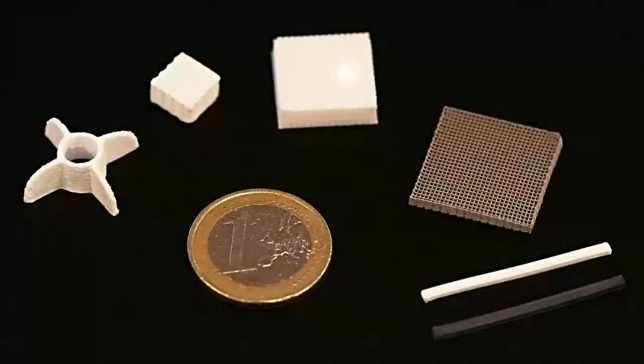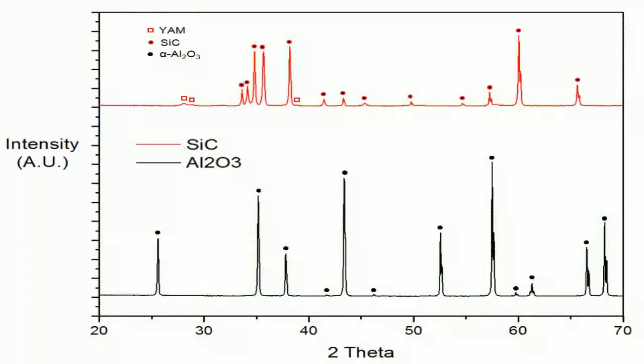And did they find anything interesting about the platelets themselves? Yes, quite surprisingly. Using advanced microscopy, like TEM and EDS, they found internal flaws within the supposedly high-quality platelets. Things like tiny salt impurities left over from processing, voids that actually appeared after heating them, dislocations in the crystal structure, even nanotwinning structures, plus steps and edges on the surfaces. They even estimated the average size of these internal defects. So even your reinforcing building blocks aren't perfect.